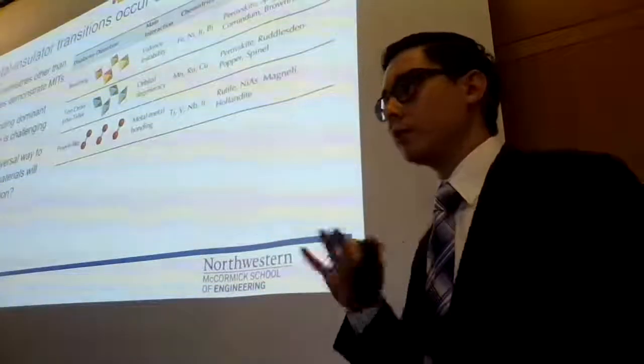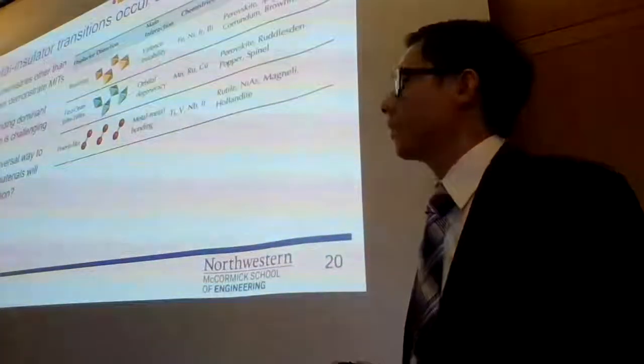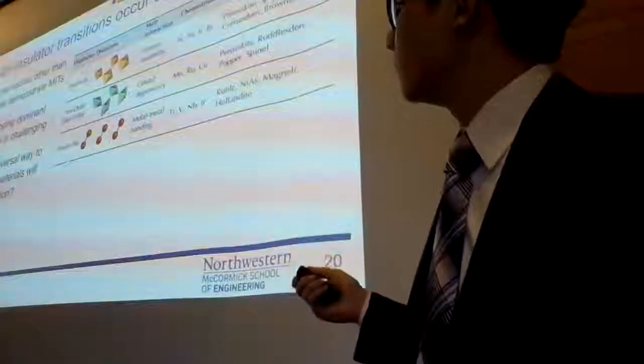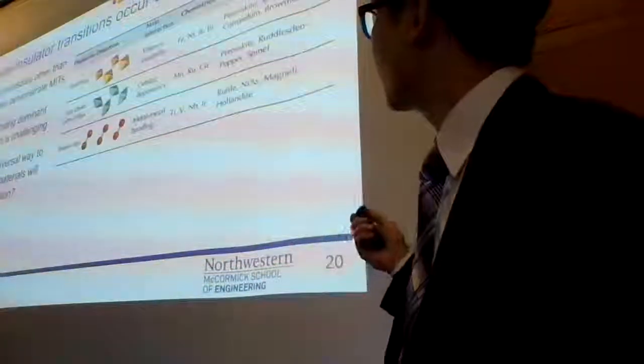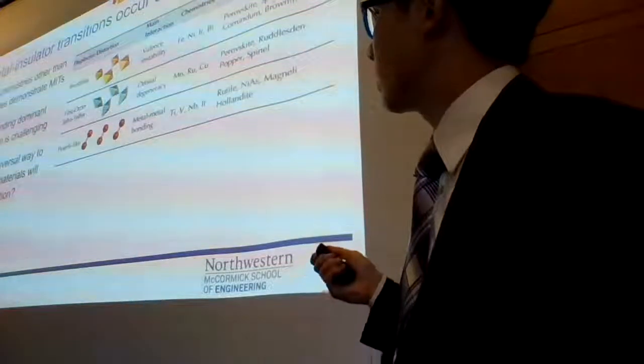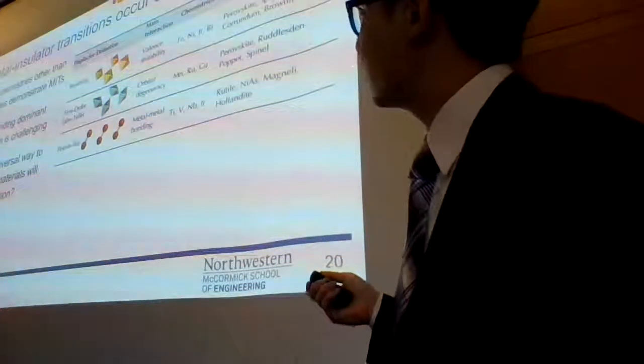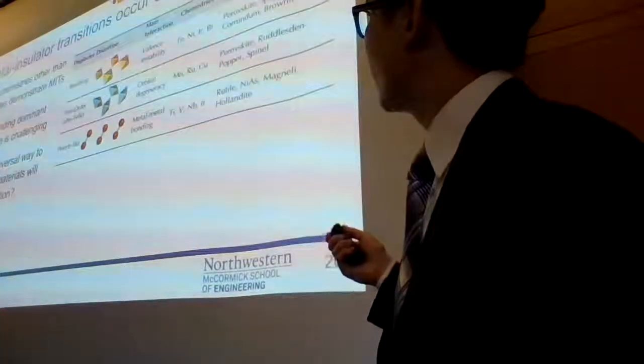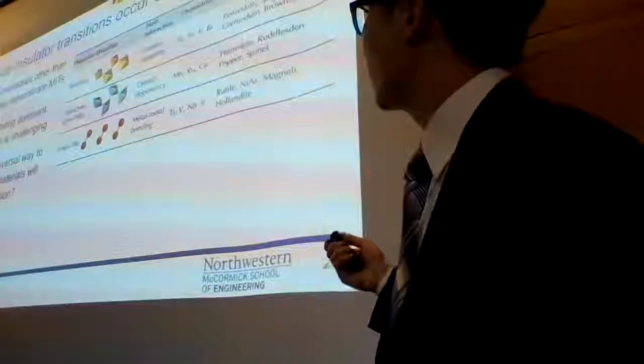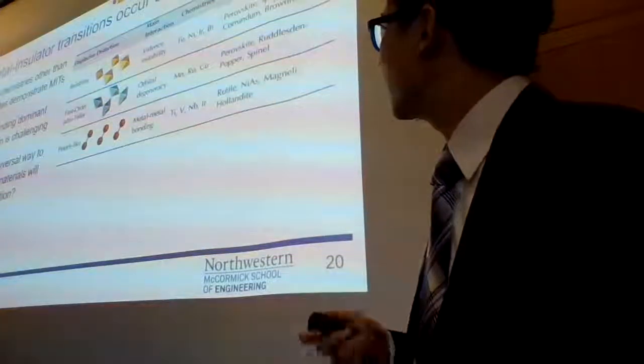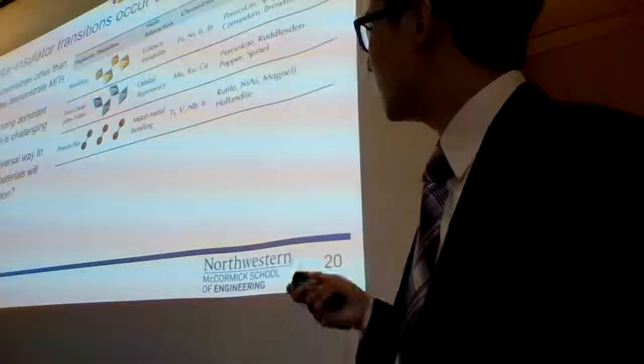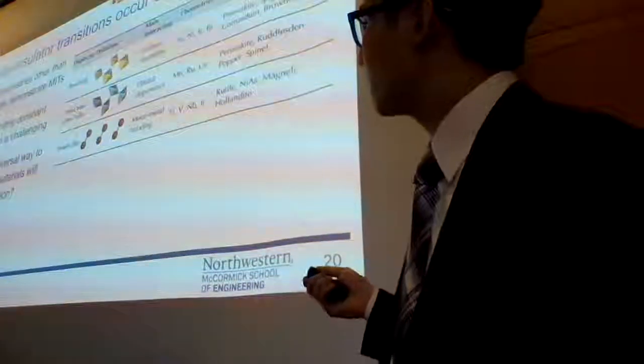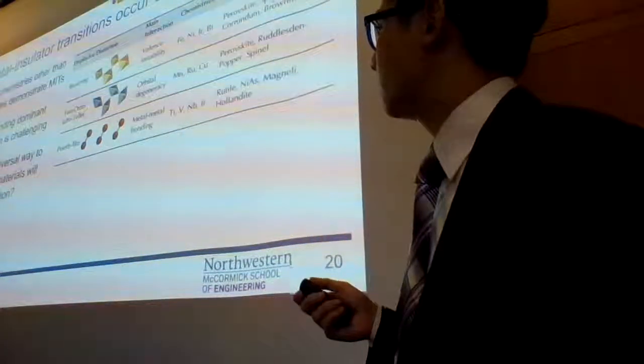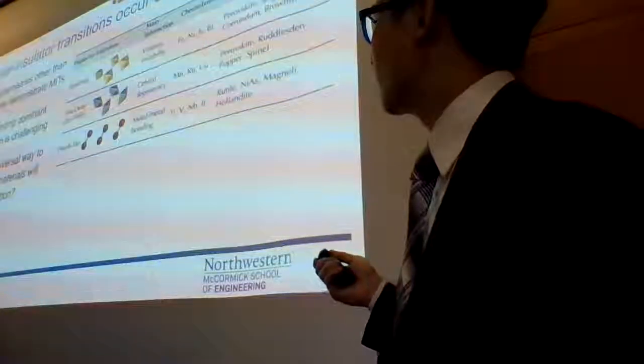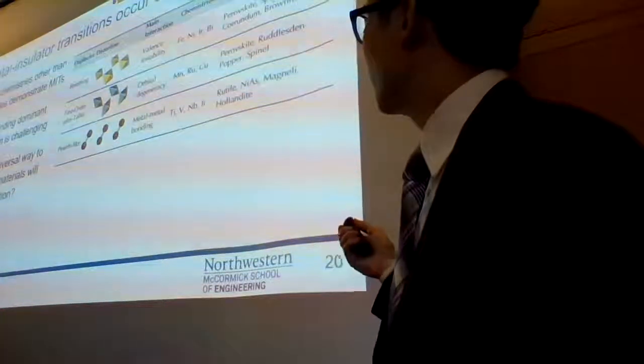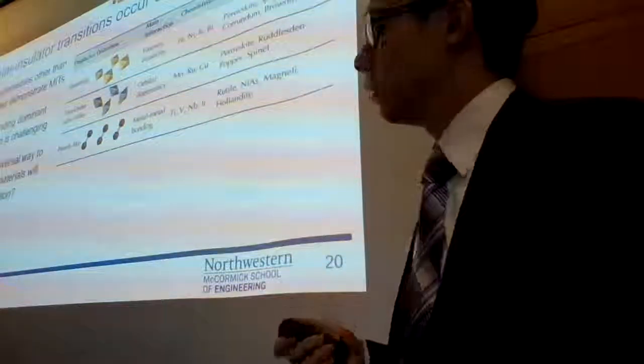So moving on, metal-insulator transitions occur in the nickelates, but they also occur in many other materials. They have a variety of mechanisms responsible for the metal-to-insulator transition. I mentioned breathing and Jahn-Teller distortions already, and while they are found in nickelates, they're also found in many other transition metal oxide families and in many different types of structures. But there are also these pyrochlore-like distortions that can lead to a metal-insulator transition, found in, say, titanates and vanadates. And these have been well studied for a number of decades as well.